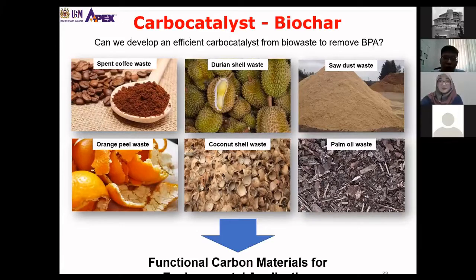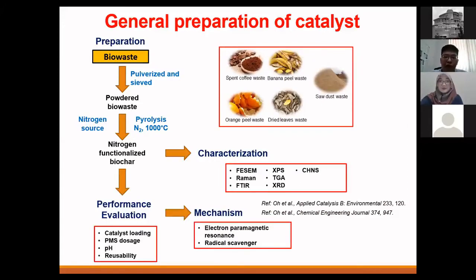So for this research, I look into how I can convert bio waste into a very effective catalyst through doping for removing emerging contaminant. Okay? So just to share with you how I did this, I looked into spent coffee waste, banana waste, sawdust, and so on, orange peel and dried leaf. Okay? And then I take this waste and carry out a pyrolysis process at 1000 degrees Celsius. And then, of course, before this, I mentioned urea is the best nitrogen source, right? So I use urea as a nitrogen precursor. And then after that, I managed to get the biochar.